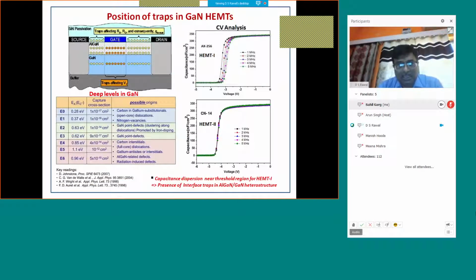And these traps are basically because of defects. They may be point defects, they may be aluminum gallium nitride related defects, or they may be surface defects or surface traps. So depending on their location, they affect my device performance. If these traps are at the surface, then they result in the gate lag. That is called gate lag, because my gate voltage is not able to introduce fast variation in my source drain current. So these are mainly taken care of by passivation. But if these traps are present under the gate or in the bulk material, then they cannot be taken care of by this passivation. Then they can only be improved by improved growth techniques.